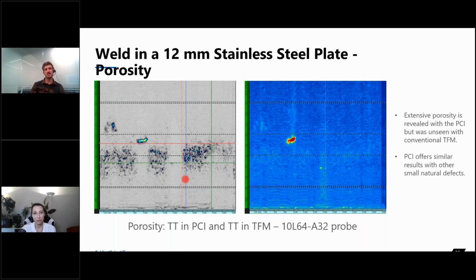But when we tested it with PCI, we noticed that our sample actually had much more than we knew. So a lot of very fine porosity, little clouds of porosity that started to appear, as well as that single pore that we could see before. So again, because it was that noisy, you can see there's a lot of noise in the signal here. Because it was that noisy, PCI did very well to contrast what was actual indication and what was purely noise. All right, next one.